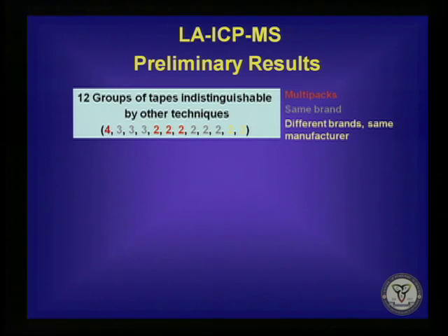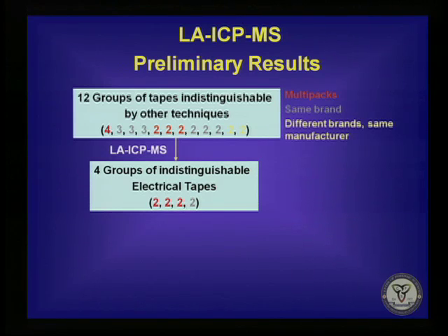We wanted to see how this related to our groups of tapes that we were not able to distinguish using other techniques. So we had 12 groups of tapes that were indistinguishable by the previous techniques. Once we did laser ablation ICP-MS on those tapes, some of which were multi-packed, same brand and different brand, we were able to further discriminate 8 groups, and we were left with 4 indistinguishable groups.